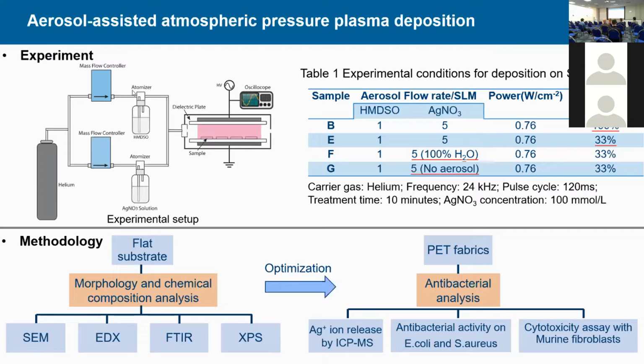The experimental conditions include continuous mode for sample B, as we see, where the duty cycle is 100%, and pulse mode for sample E with 33% duty cycle, sample F with no silver nitrate in the aerosol, and a control sample G with no aerosols. The treatment time in the experiment is 10 minutes, and the silver nitrate concentration is 100 millimole per liter. After deposition on silicon substrate, the coatings were analyzed with SEM, EDX, FTIR, and XPS to study the morphology and the chemical composition.